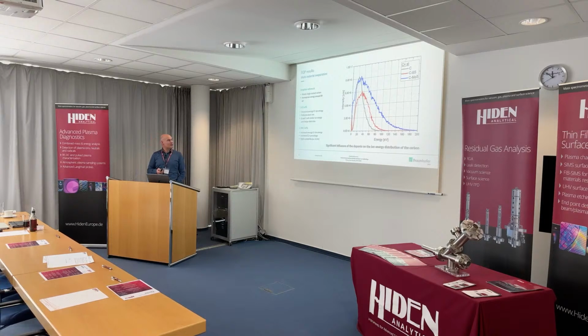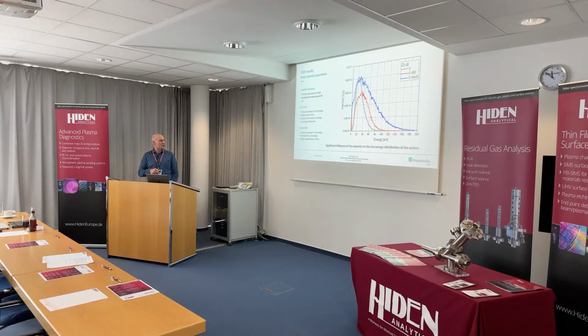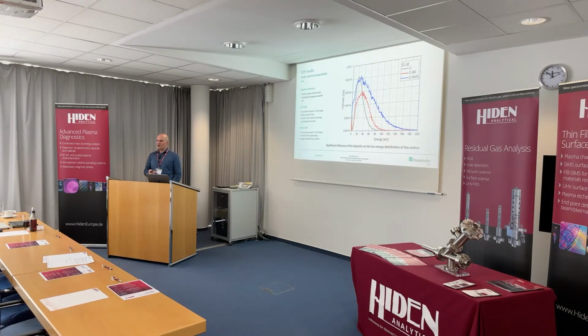Okay, now I put together the C plus for the 3 different cathodes. All the other process parameters are the same. We see the reference in carbon, and then some higher ion energies if we put boron in it. And if you put molybdenum in it, then it moves straight to the right side. And of course, we affect the properties of our films with it. How we do this, I haven't brought here. I think this would be too much, but we can use this device very well for our measurements.